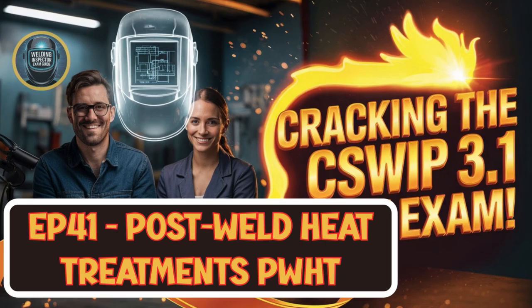First up is the maximum heating rate. You can't heat it up too quickly. Why? Because you want to avoid large temperature differences within the part itself. We call these thermal gradients. If one part gets way hotter than another part too fast, the expansion differences can cause the whole thing to warp or even crack. It's like pouring boiling water into a cold glass sometimes. Right, thermal shock, basically. Exactly.